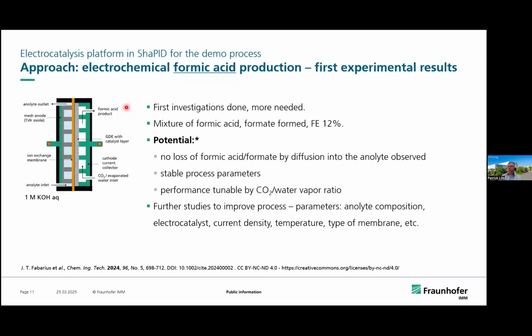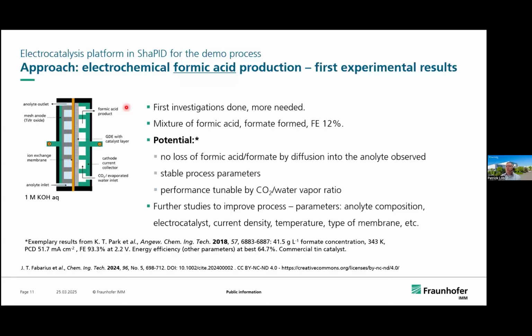To point out what the motivation was and what the potential behind this approach is: we reached about 1 molar. If you look in the publication from K. T. Park, he ended up, for example, with 40 grams of formate per liter, also roughly a 1 molar solution, with a partial current density of around 50 milliampere per square centimeter, a Faraday efficiency above 90%, and a low cell voltage of 2.2 volt. He also calculated energy efficiency and other parameters, at best amounting to 65%, and he used commercial tin catalysts. In our project, we also developed our own catalyst, so catalyst variation is still a point of investigation in our case.